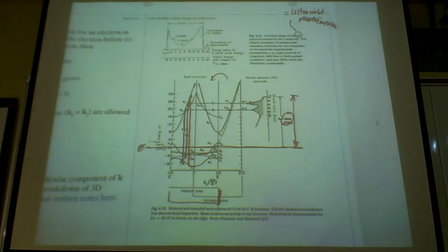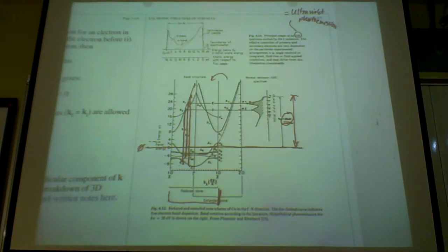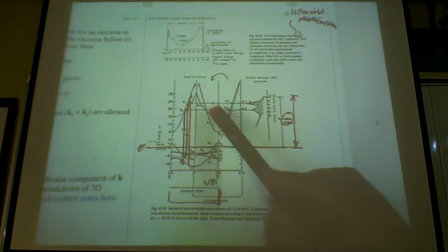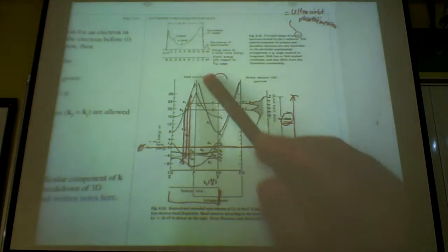Because of the boundary condition that you try to describe in different directions, because of the lattice structure that you have, you create a gap, and you create a different band structure. If you ignore this dashed line, you will have this little gap in between, and that is the result of the crystal structure on your electronic band structure. Okay, so they are related. This is why you have structural property effects: the physical structure of your material directly controls the electronic structure in terms of the band structure like this.